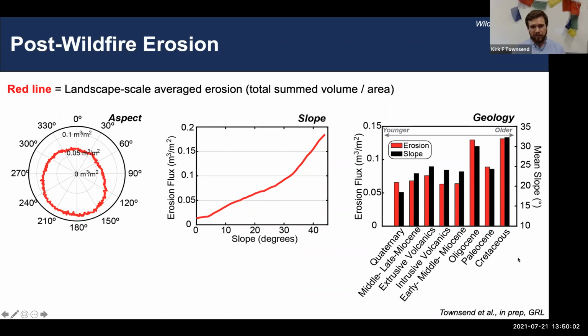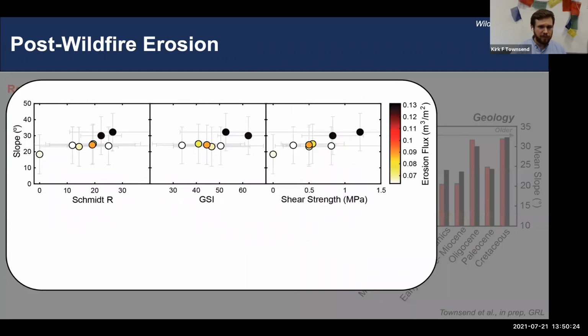So we see that erosion appears to be increasing with the increasing stratigraphic age of the underlying bedrock. But slope is also increasing across the same gradient. Now remember that rock strength also increases as rocks get older here. So if we compare the erosion from each formation and the slope from each geologic formation against strength, we find these really interesting relationships here. So we're looking at 3 different strength metrics on the x-axis, Schmidt R, GSI, and shear strength against slope on the y-axis. And then these points are colored by the erosion. So darker colors are more erosion and lighter colors are less erosion.